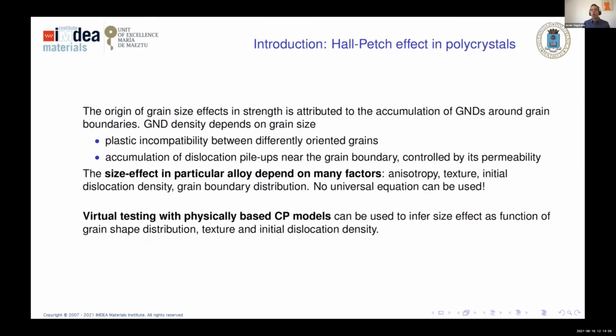boundaries. Let's explain this. When I have a grain that wants to deform in one direction, and another in the other direction, because crystal plasticity is very anisotropic, what I have are some strains, okay, that are not homogeneous within the grain. These strains have a variation from the grain boundary to the interior. In order to accommodate this gradient of the plastic strain, we need to put into the material some dislocations of the same sign that somehow cover this incompatibility in the deformation, okay? These are what we call GNDs and are responsible for that. Of course, for the same change in plastic strain, the smaller the grain, the larger the gradient, and then the larger the amount of GNDs that we have to put there.